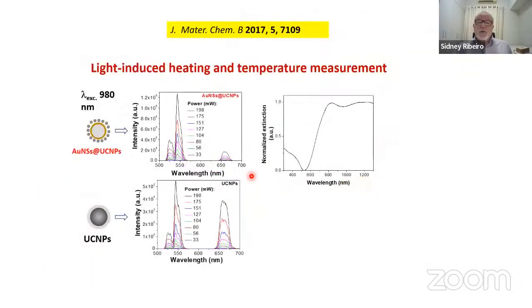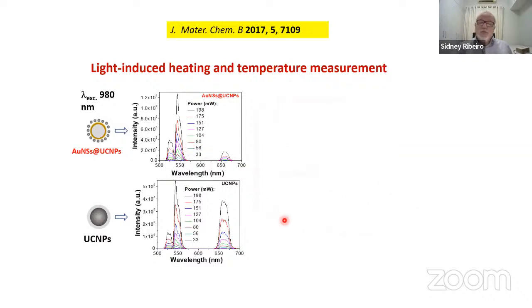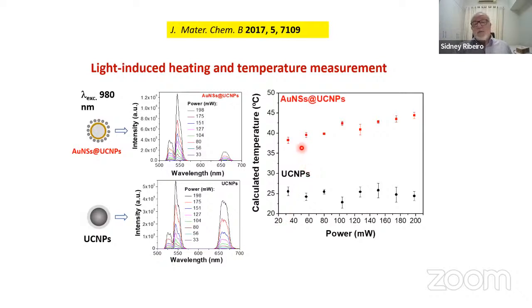These are some results. So you have here the absorption of these gold nanoshells, showing that the plasmon is in the infrared region of the spectrum. So when you shine in the infrared, you observe the upconversion emission from the nanoparticles, and also you observe heating. So this is the temperature for the gold nanoshell samples. You observe the increase in the temperature with the power of the pumping laser. And when you don't have the gold, temperature is always the same. So we are showing here this nanoheating process, and we are measuring the temperature at the same time.